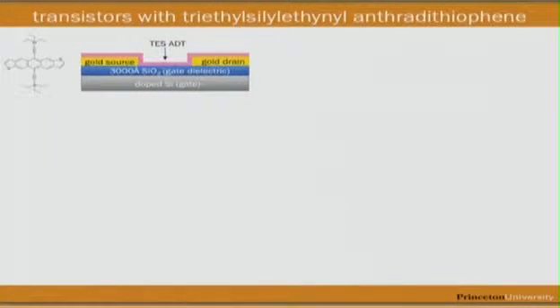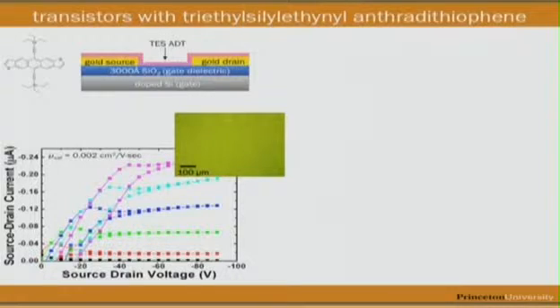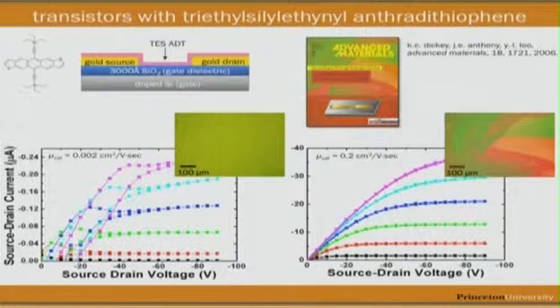Now, we can make transistors out of these materials. So we start out with this TES-ADT that we spin coat or we cast as a thin film. The devices are pretty bad, again, because there's no long-range order and minimal pi stacking. But if we crystallize the film by exposing it to solvent vapor, you can see that the mobility increases by 100 times. Okay? And now this mobility is relevant for the kinds of applications I was telling you about.